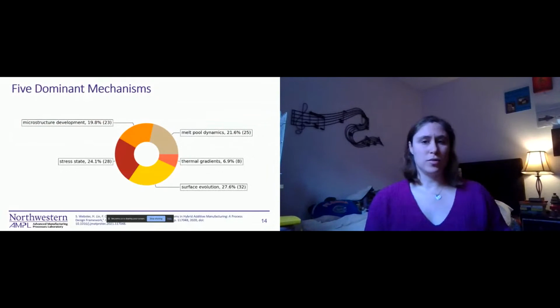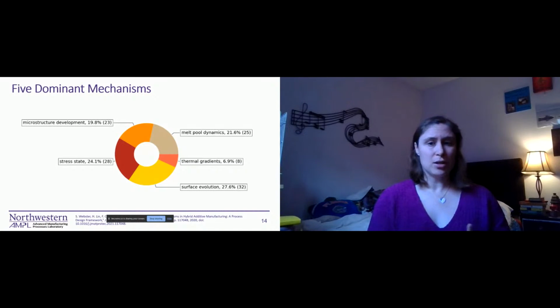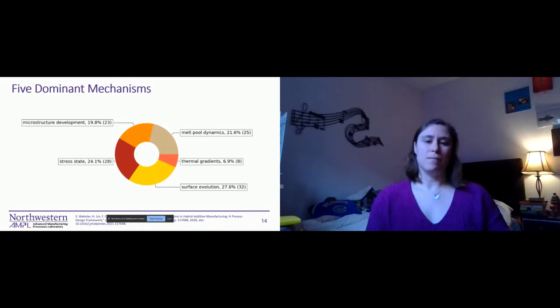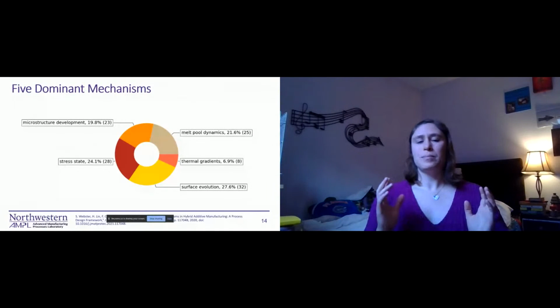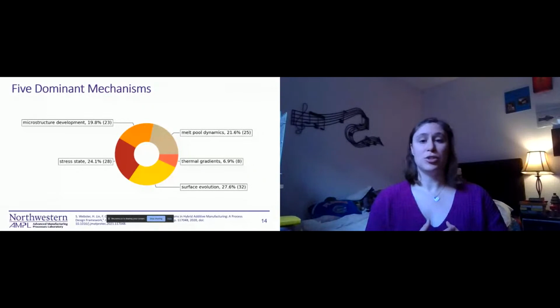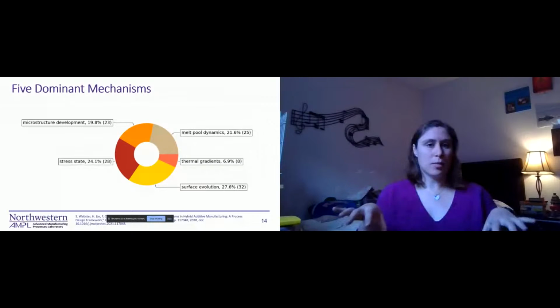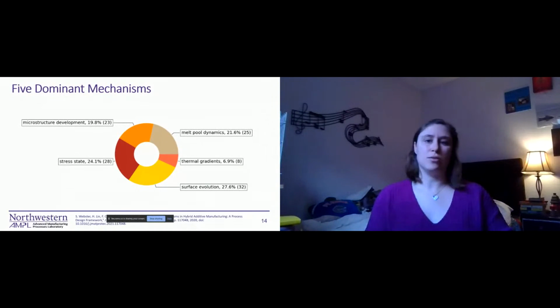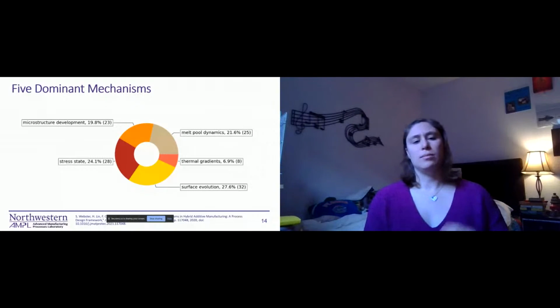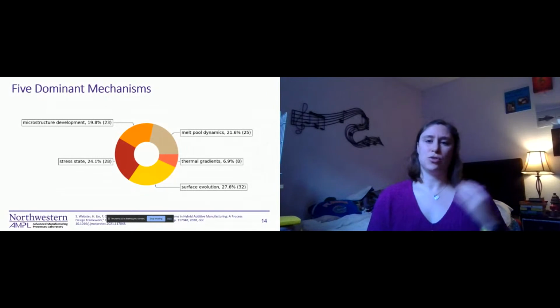And so across all of this research, the main mechanisms that were used to control the properties of a material were melt pool dynamics, microstructure development, the stress state, surface evolution, and thermal gradient. Here you can see the relative amount of research being put into each of these categories. But overall, the most common thing to control was the surface evolution, in which the hybrid processes essentially affect the surface properties. So trying to mitigate surface roughness of the materials, either through machining or laser remelting. Residual stresses are also a well-known thing in AM materials. And so the stress state was often controlled through a secondary energy source.